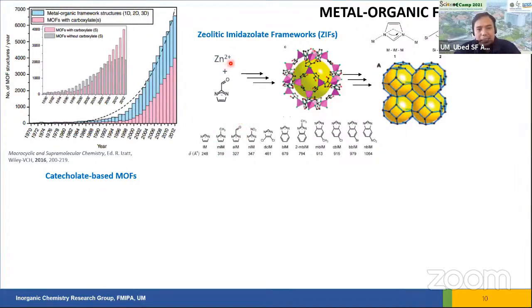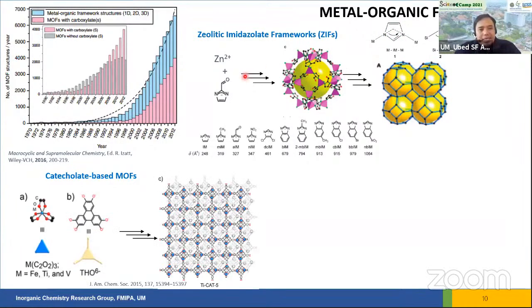For example, by reacting zinc 2+ ions with the imidazole organic ligand, we can form a beautiful structure. The structure itself resembles zeolite. That's why these materials are called zeolitic imidazolate frameworks, or ZIFs. The structure of zeolite is usually formed by silicon and oxygen, and the angle resembles the one with the organic ligand in the ZIF structure. That's why it's called ZIF materials. So this is nitrogen, and the previous one is the carboxylate.